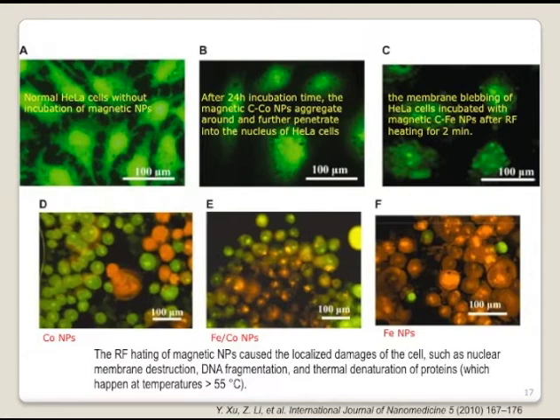The image you see is membrane blebbing of the HeLa cell incubated with carbon-coated iron particles, just for 2 minutes. You see what happened. Then in images D, E, F, we compare 3 different nanoparticles to see their killing effect. This is cobalt nanoparticles, this is alloy nanoparticles, this is iron. Cells dyed green are still alive. Orange or even brownish colors mean the cell is already dead. So apparently iron nanoparticle is the best among these three.